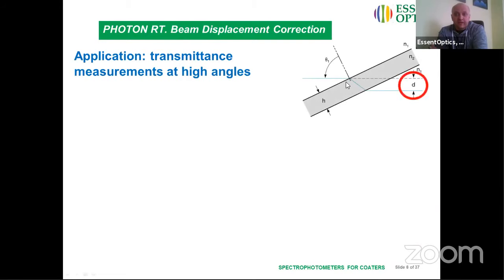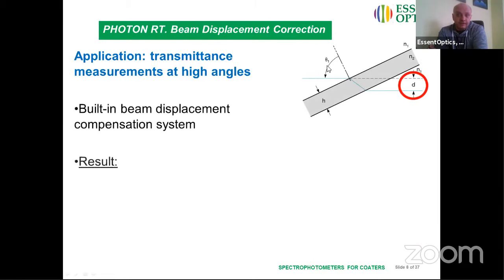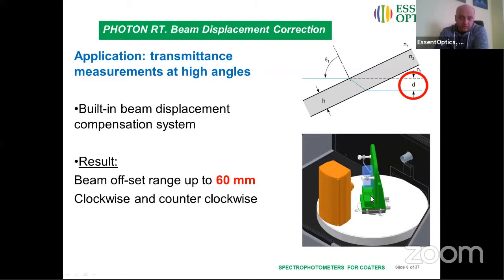Typical application for flats is when you measure different angles of incidence, so you have a beam displacement, and we can cope with this, and our system can automatically control this displacement up to 60 millimeters, both positive and negative, which is a very unique feature not found in any other system on the market. Like this.